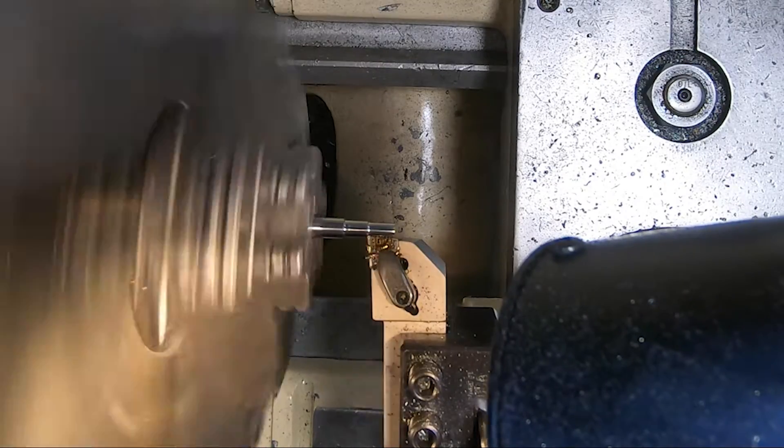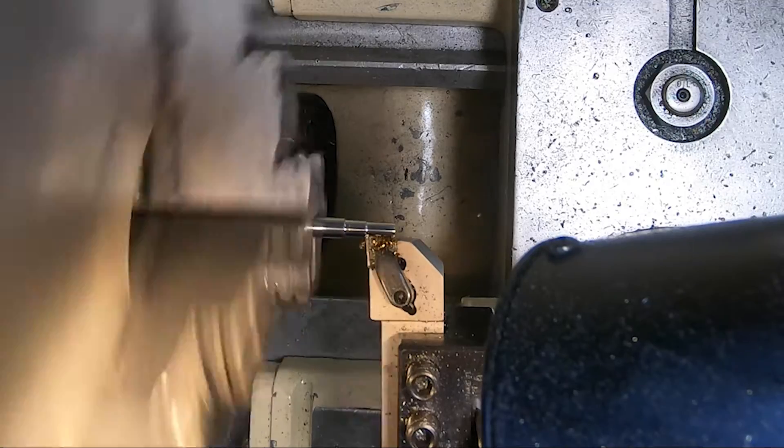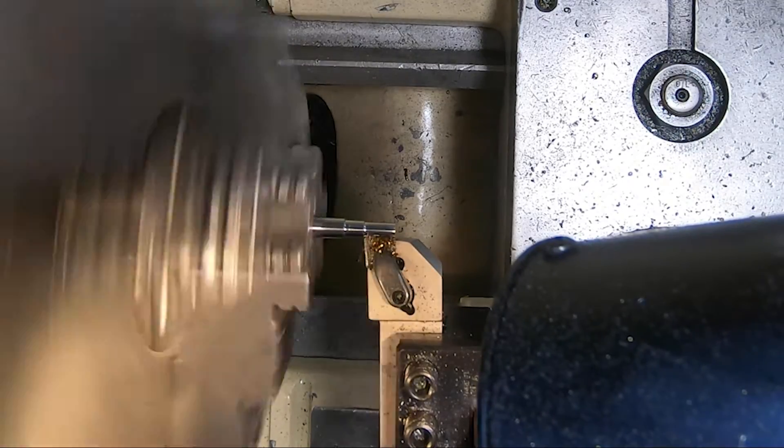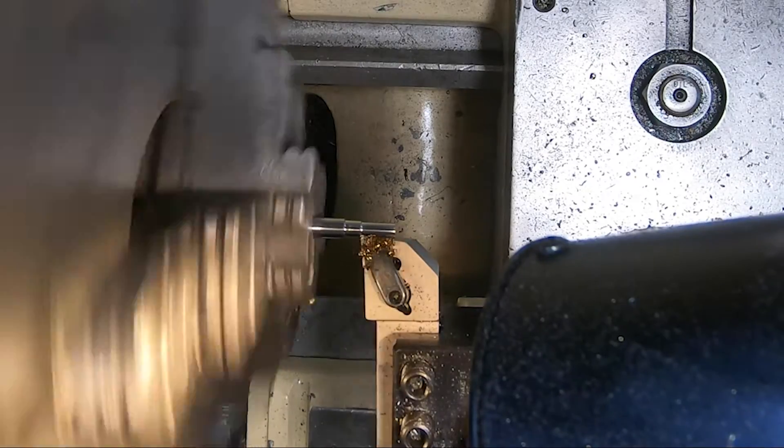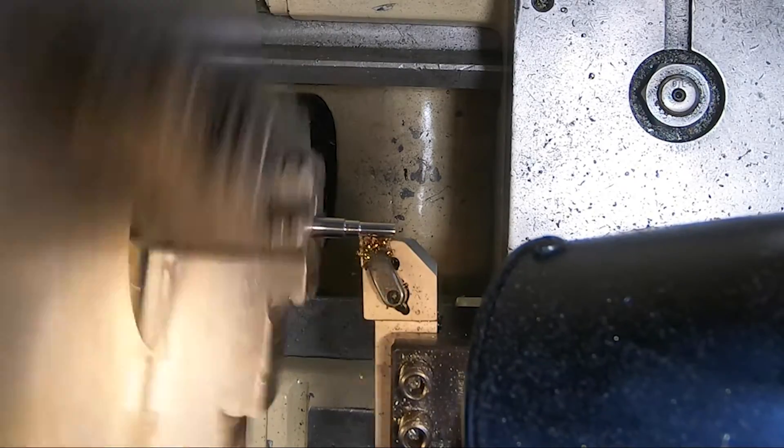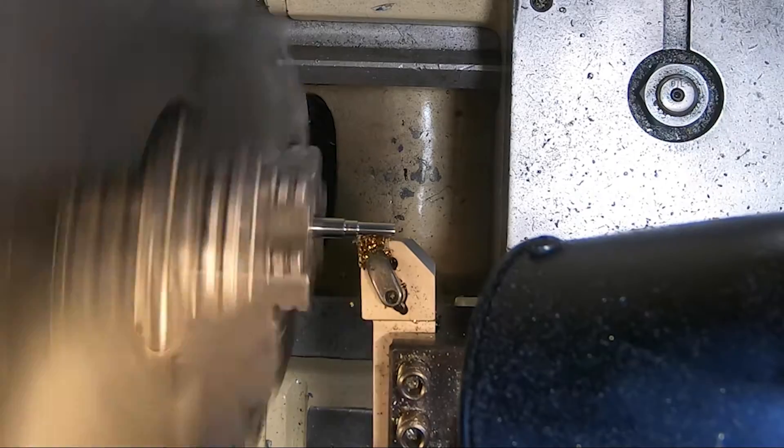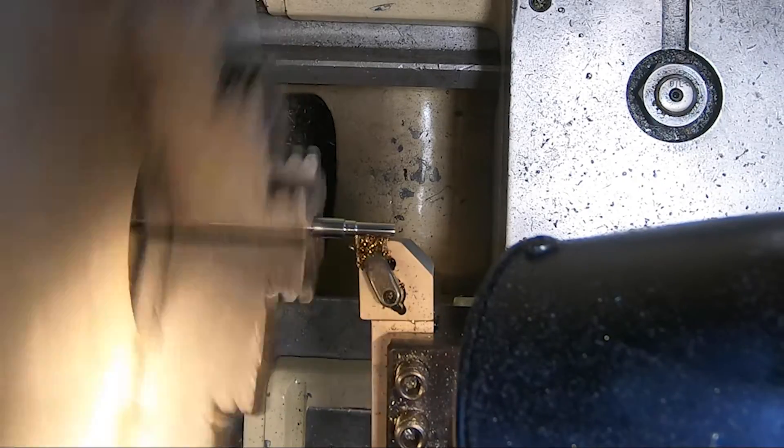So knowing that, let's repeat the experiment, but increase the depth of cut to the nose radius or 30 thousandths. And you can see this is going great, leaves behind a great surface finish, makes a nice chip that breaks easily, and those chips are that straw yellow color that everybody strives for. So I'm pretty satisfied with this cut, and this goes pretty well.